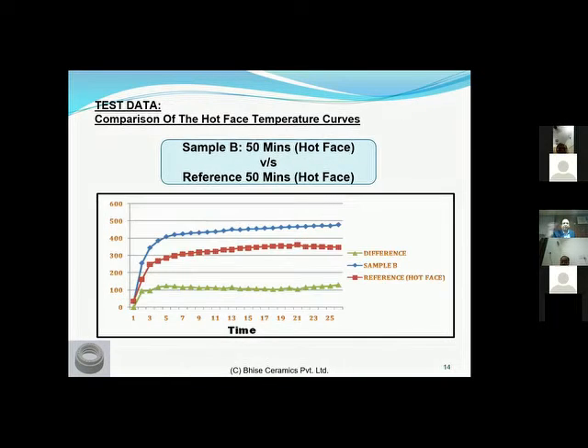We did the same thing for 50 minutes. Over here, we got about a 120 degrees difference. But you can see pretty much the same thing: the curve is far steeper, and you're having stabilization fairly quicker than the earlier one. So in both cases, you can see that usage of ThermProtect is really giving you a drastic difference.